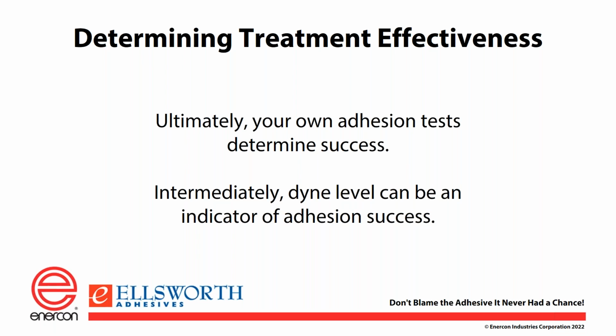We get asked a lot, mostly by aerospace, how do I know that I've got a good bond without breaking it? And the way we do that is try to control as many things in the process as we can before it comes into our system and then out of our system. So by that I mean, I can predict with a very low standard deviation of error how something is going to come out of my flame or my plasma system if I know the material that goes in. So we have to monitor each of those steps and know where we're at, know how clean the material is, know what the surface energy of the material is, and all of those things, and then know what level of surface energy we need for a good bond to come out on the other side and have a good part. So that's how we try to control each of those steps.